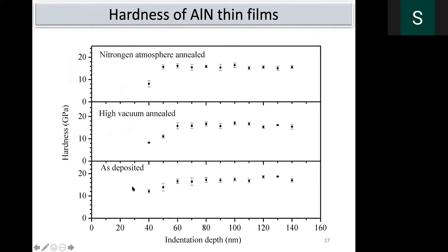The amorphous one, as the first study, has shown close to 18 GPa hardness, but these are all only 16 GPa hardness that we see with depth. The main reason behind it is the amorphous nature of the material. When you reduce the grain size, the hardness increases, but when you anneal them, the grain size increases and the hardness comes down, which I will explain in a little later stage. That's the reason. Here we have seen the hardness, but both are looking almost similar.